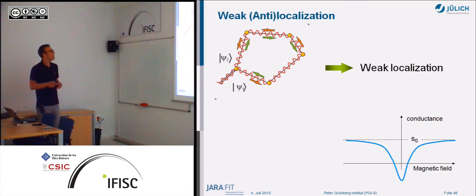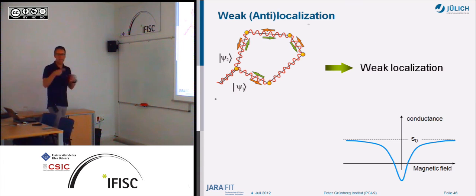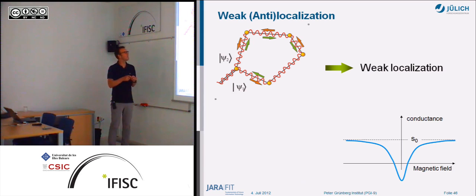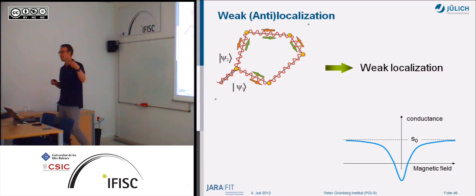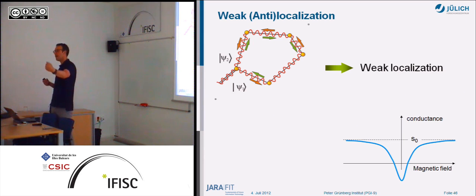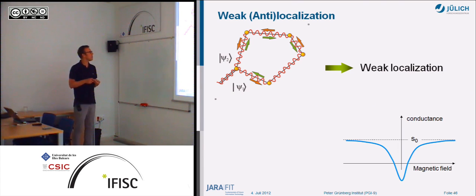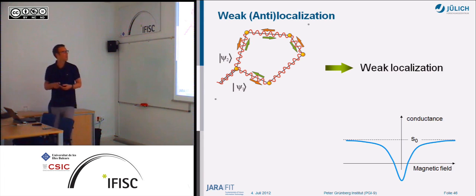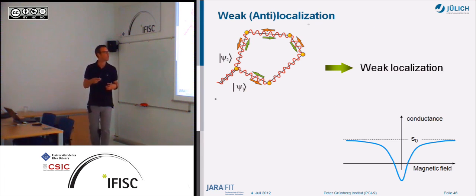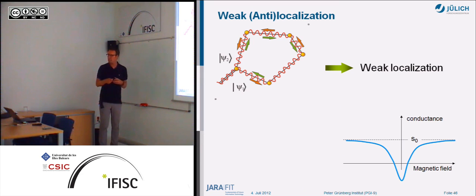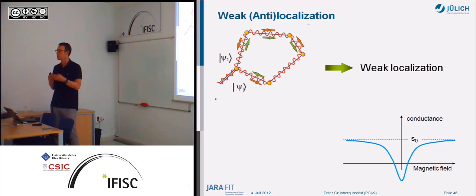So what is that? Weak localization, you probably know, occurs in diffusive systems: the electrons come here, they can either go that way or the time-reversed path, and since they meet at the starting point again after going around, you have constructive interference. That means you have a higher probability for backscattering, and this increases your resistance at zero magnetic field. So the conductance goes down at zero magnetic field, because you not only have this loop but also other sizes of loops, since you have a random system with a random distribution of scattering centers. But in all cases at zero magnetic field, you always have constructive interference.